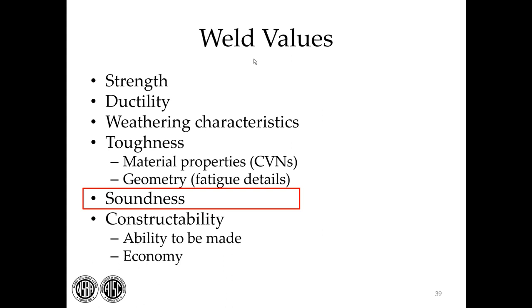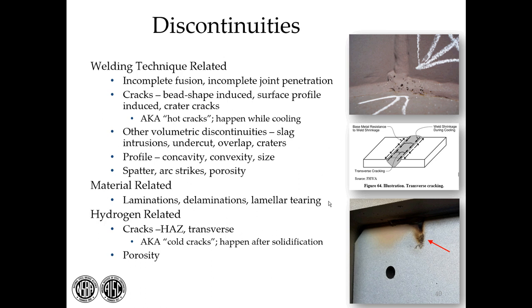So we talked about the weld metal properties. Now let's talk a little bit about soundness, making sure that we have a quality weld from the defect perspective. So here are some general categories of discontinuities that you might encounter in welding. Many of the discontinuities are related to welding technique. Incomplete fusion, if you don't tie the weld metal to the base metal, incomplete joint penetration, various types of cracks. These are the type of cracks that happen while the weld metal is cooling. So they're also known as hot cracks.